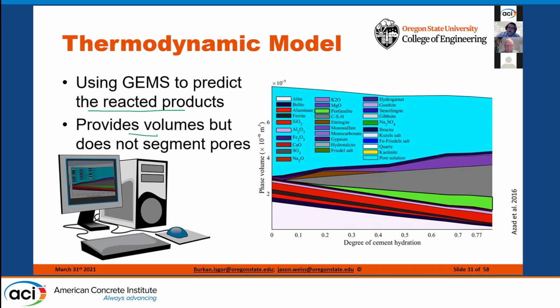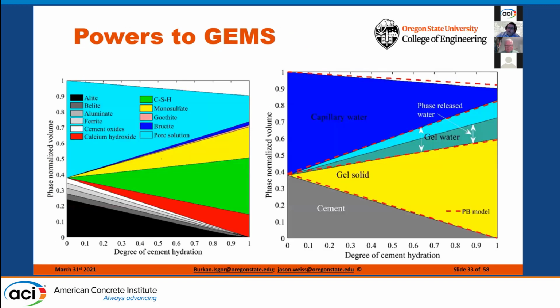But this provides the volumes of the materials, but it doesn't really tell us how they're broken up into different pore sizes, right? So what we want to do is talk a little bit about this. And what I want to mention is we've actually used an approach that really takes exactly what Powers did, and it overlays it on the outputs that we would get from energy minimization. So here you can see, again, Powers is shown on the right-hand side, the gray from the cement, the blue from the capillary water, the gel water here shown in aqua, the gel solid shown here in yellow. And we can take the GEMS output and we can map these directly to the types of pores and the types of phases that we have from Powers' model.